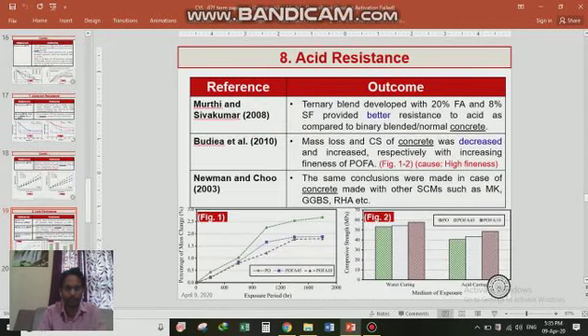Regarding acid resistance, Murthy and Shivkumar concluded that the ternary blend developed using 20% fly ash and 8% silica fume showed better resistance to acid compared to that of binary blended or normal concrete. Budia et al. in 2010 showed, as shown in figures 1 and 2, percentage mass change and compressive strength. Figure 1 is related to mass change percentage, and figure 2 is related to compressive strength, at different fineness, particle passing like 45 micron, 10 micron. This is for 10 micron, this is for 45 micron, and this is for control concrete.